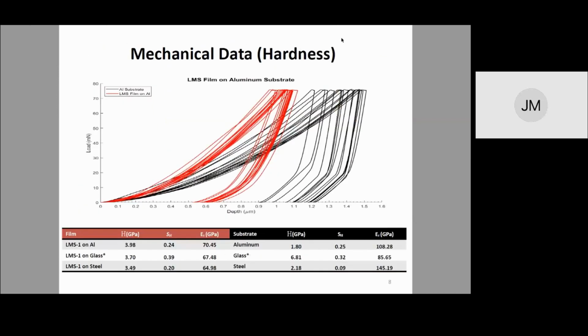So here we can see a graph from our Nanovea nano indenter on the aluminum sample. The black lines are the individual tests on the substrate itself that had a standard deviation of about 0.25 over 15 tests, and then the red lines are individual tests on the film itself. The tables below, the colors correspond to the colors in the graph. So the red is going to be the film data, and then the black is the substrate.